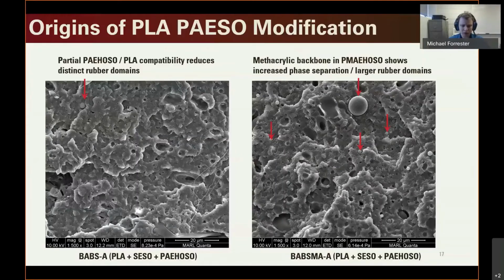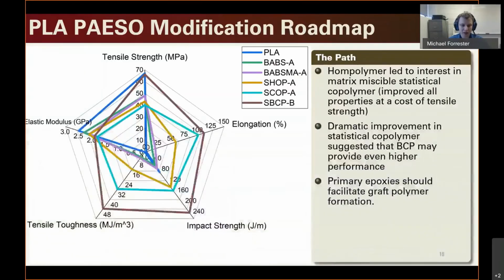And we started thinking about that. And one of the things that we looked at is the SEM imaging. And what we saw is that in the acrylate systems, you see a few of these microphase separated compounds, but not as much as you'd ideally like for something that would be a good impact modifier. In the methacrylated system, you do see a bit more of those phase separations, but you're still not seeing the increase in the impact resistance. So we got to thinking about, why is that happening and what can we do to improve things?